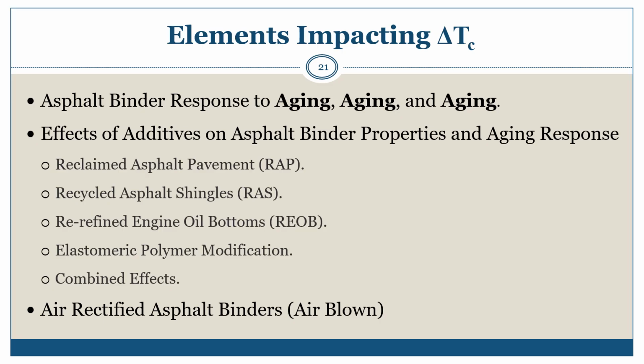As we just discussed, asphalt binders blended with polymer modifier can also be evaluated for delta Tc. However, there are concerns on the validity of characterizing polymer modified asphalt binders using delta Tc. Some features of elastomeric polymer modification may have a worsening effect on delta Tc and therefore make it appear as if the polymer modified asphalt binders are exhibiting diminished durability. Combined effects of all these factors should also be considered. One element that we do not speak much of in the U.S. are air-rectified or air-blown binders. Air-rectified binders are somewhat pre-aged and would also affect the results of delta Tc.